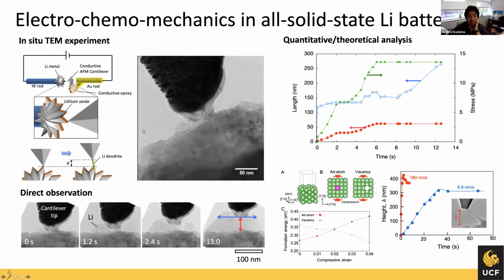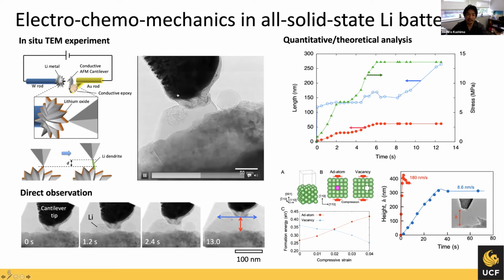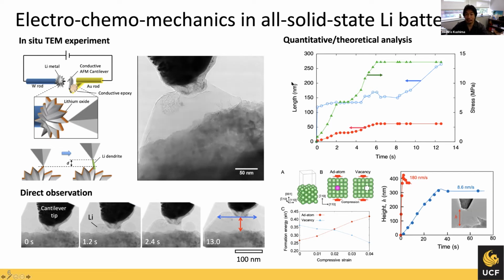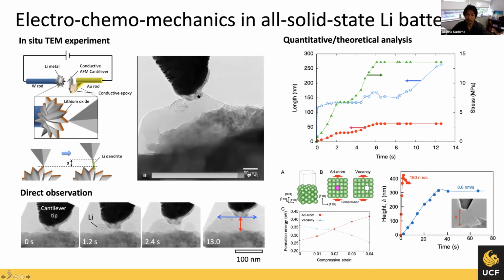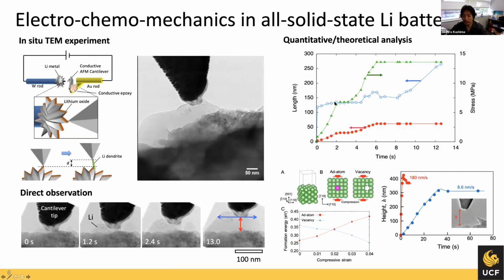If you apply the bias, you can see the dendrite starts growing at this cantilever, and as it grows, it's going to push this cantilever away from the electrolyte. By measuring the displacement, you can quantify how much force has been applied to this dendrite and also to the cantilever. And you can see, according to this applied force, the growth direction will change from vertical growth to horizontal growth once it reaches the threshold.